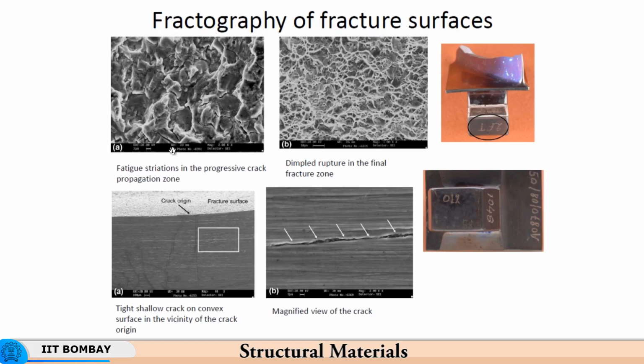area where the crack originated, one found a tight shallow crack on the convex surface in the vicinity of the crack origin. So what it means is that already a tight shallow crack was present. What we mean by tight shallow crack is that the crack length is very long, but the radius of curvature is very sharp. So basically it was a tightly closed crack. It was not something that had opened up significantly, and the radius of curvature at the two ends was